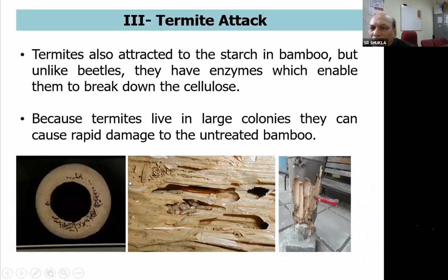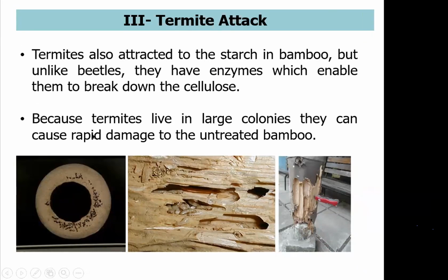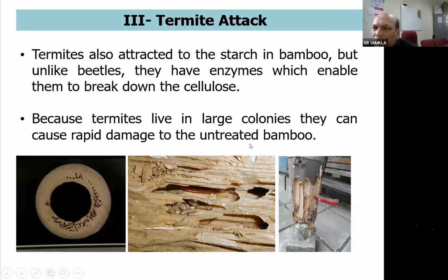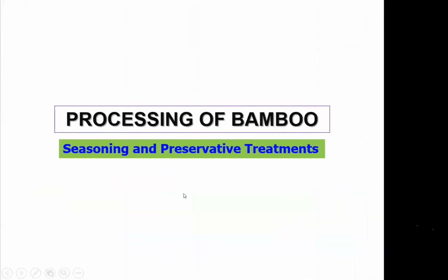You might have seen small holes in the bamboo if it is not treated properly, and this makes the bamboo weaker, and ultimately the product becomes unusable. Third is the termite attack. The termites are very prevalent in our conditions. They get attracted to the starch which is present in the bamboo. Unlike beetles, they have enzymes which enable them to break down the cellulose. These termites live in large colonies, and they can cause rapid damage to untreated bamboo, and this makes the bamboo weaken and ultimately destroys the whole structure.